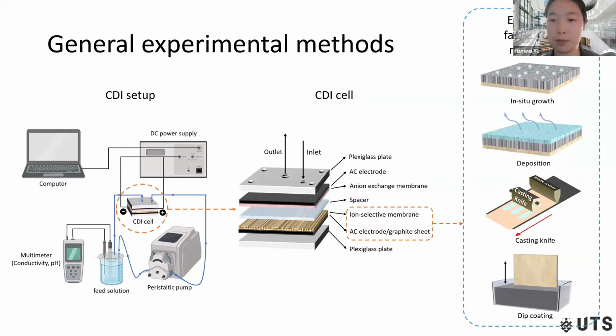Now, I would like to introduce the general experimental setup and methods used throughout my research. The CDI setup consists of a DC power supply, a CDI cell, a pump to circulate the feed solution, and a multimeter to monitor the conductivity and pH. The CDI cell is composed of two graphite-supported electrodes, a spacer, an ion-selective membrane (AEM), and an activated carbon electrode. The electrode fabrication methods used in my cathode fabrication include in situ growth, deposition, casting knife, and dip coating.